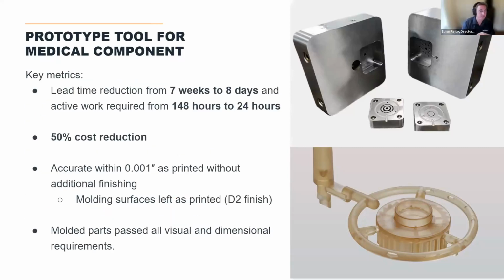A couple of key metrics here. Lead time was reduced from 7 weeks, which is what they estimated it would have taken if they had to outsource this tool, because it featured some sinker EDM work that they weren't capable of doing in-house, to just 8 days. Active work went down from 148 hours to 24 hours. A 50% cost reduction here. The entire tool was accurate within 1 thou without any additional finishing.